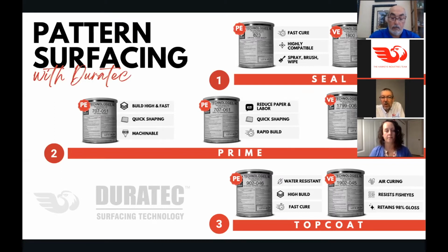When you put primers over a porous substrate, the resins in the primer will tend to soak into that substrate. Whereas if you put a sealer on it, it won't soak in. The sealer has done the soaking in. If you suck the resins out of some of these primers on a very porous surface, what happens is you get a dry, powdery surface on there. It doesn't retain all its physical properties because that resin has been soaking into the substrate. Frequently on low density foams and wood, that happens a lot. Once you've primed that, our top coats can be used over the top.